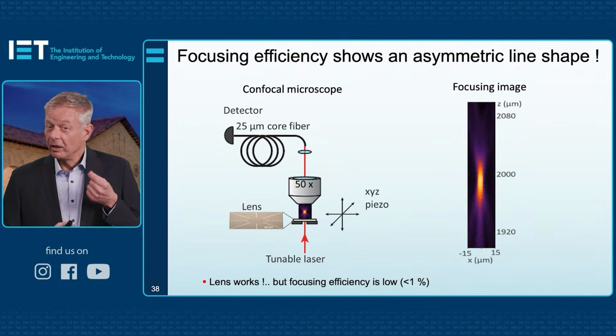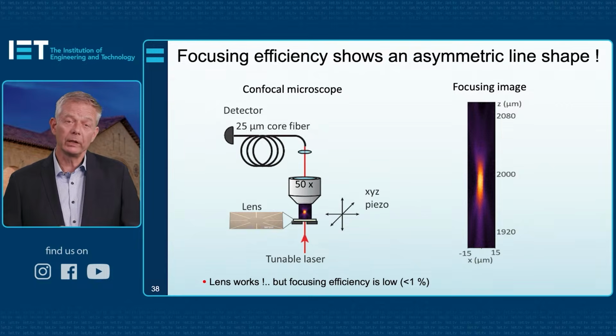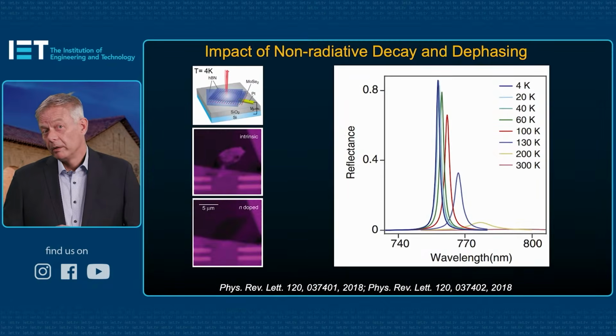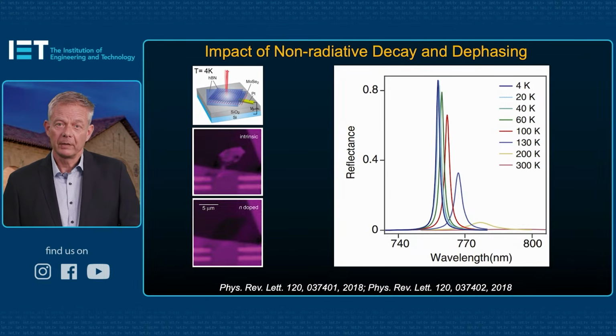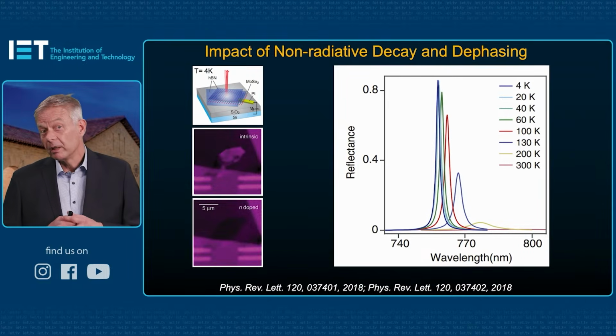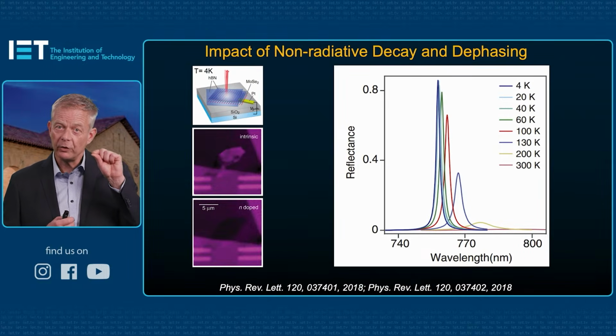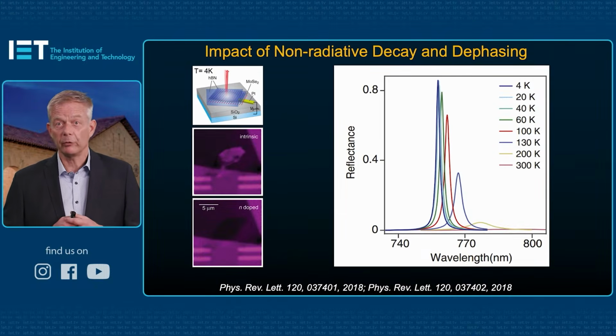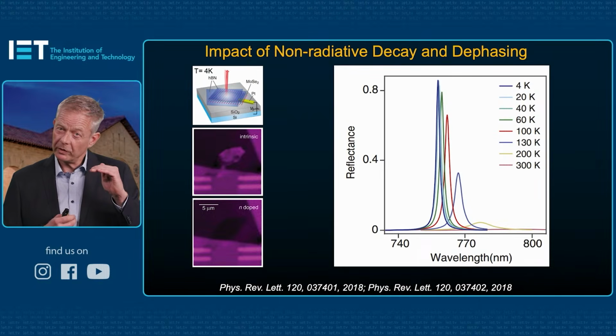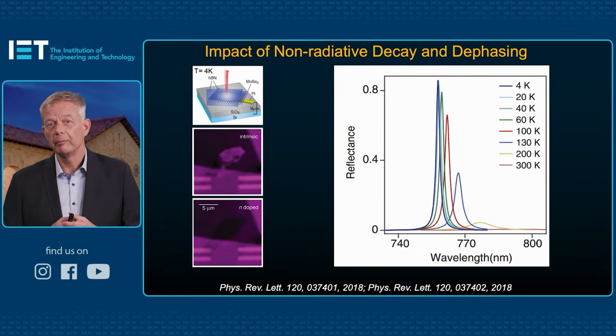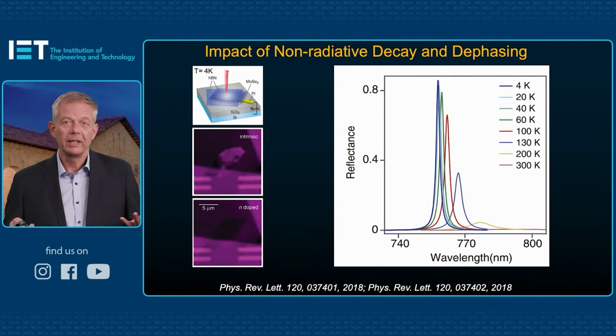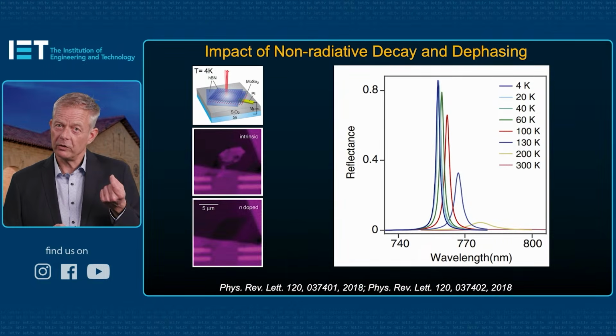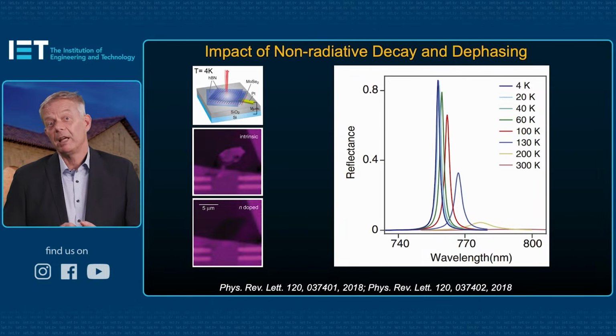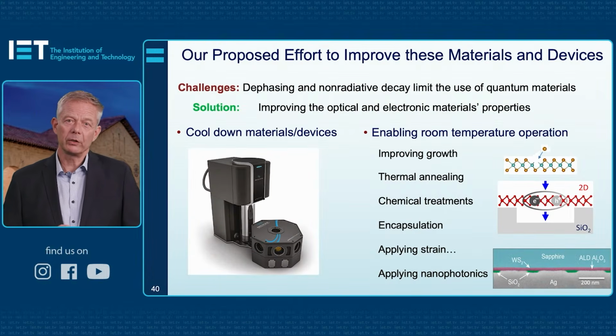Looks very promising, but unfortunately the efficiency turned out to be only about 1%. So a new question comes up: can we make it better? Going back to the earlier work on the highly reflective atomically thin mirror, the reflectance was great at 4 Kelvin, or really low temperatures, but as we increased the temperature to room temperature, about 300 Kelvin, the reflectivity completely dropped. So here's a wonderful opportunity for physicists and clever engineers to see whether somehow we can regain that beautiful reflectance and all of the wonderful resonances and optical properties at room temperature, so we can harness them in real devices.